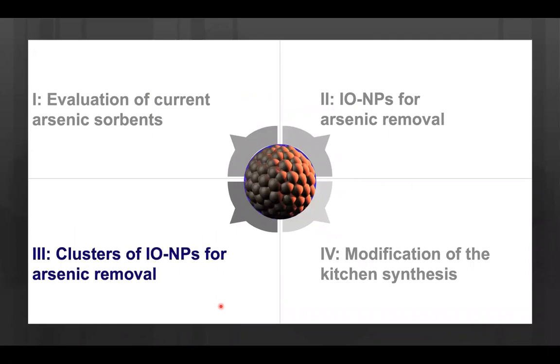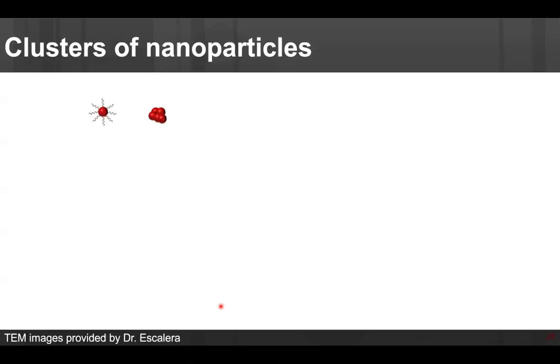For that, at that moment, we found a different synthetic methodology to create clusters of nanoparticles. And I worked not only on assessing the arsenic removal performance, but also on understanding the mechanism of that synthesis. When we talk about nanoparticles, if we are using a synthetic method that is inorganic and very fancy, we will get something that looks like this, right? You have the nanoparticle that is well-defined, and you have a surface coating that allows the nanoparticle to be by itself. If you remove this coating, then you start to have small agglomerates. Maybe 2 or 3 nanoparticles, but still, you cannot find them individually now.